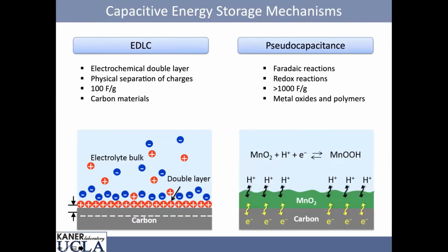One way to do this is to take a material that is a pseudocapacitor. Manganese dioxide is the material. If you look at any primary battery that you have, like an AA or C battery, it's all filled with MnO2. We have these dollar stores, where you can buy 10 of these for $1. So you can imagine the amount of manganese dioxide in your battery is worth less than a penny. So this is really cheap stuff. However, it's an insulator. So a C battery or AA is filled with about 40% carbon black to make this conduct.